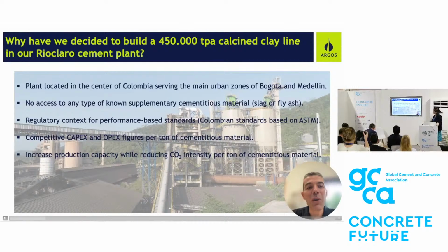Second, that plant has no access to any type of known supplementary cementitious materials such as slag or fly ash. Third, the regulatory context for performance-based standards in Colombia, which is inspired by ASTM standards, allows for blended cements to be used all the way from residential applications to infrastructure projects. Fourth, when we compare CAPEX and OPEX figures side by side for the clinker process and a new calcined clay process, we found that in both terms, calcined clays were more competitive. And finally, when we decided to increase production capacity, we were also looking at ways to dramatically reduce our CO2 footprint, and calcined clays were the path forward.